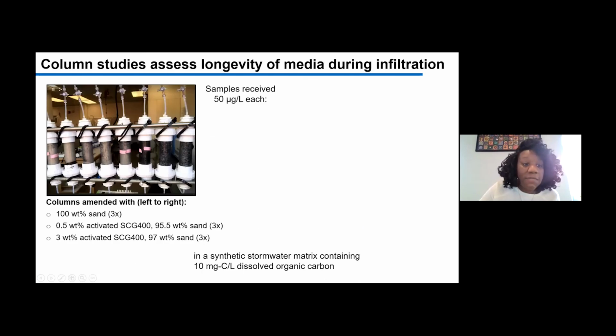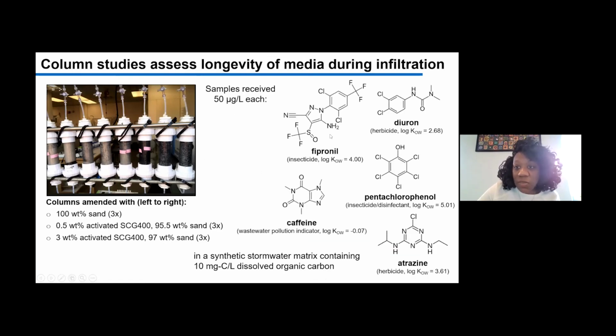So here I have an image of columns that we've built in the lab. And here we have sand-only columns, and we have increasing amounts of the coffee ground biochar. And we are feeding synthetic stormwater into these columns, each at 50 micrograms per liter. And here are the trace organics that we have added into the synthetic stormwater that's being treated by these columns. And the highest weight percentage that we selected was 3 weight percent. That's shown in these triplicate columns over here.